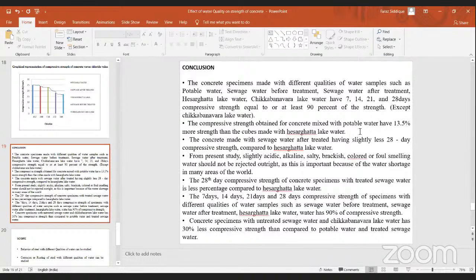And the compressive strength obtained for concrete mixed with potable water was 13.5% more than the cubes made with Hesarghatta lake water. The concrete made with sewage water after treatment had slightly less 28 days compressive strength compared to Hesarghatta lake water. From the present study, we understood that slightly acidic, alkaline, salty, brackish colored or foul smelling water should not be outright rejected. Because if we do not have any other sources of water which we can use for our concrete, I should not reject it outright.